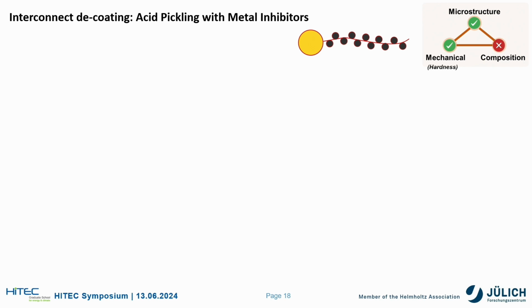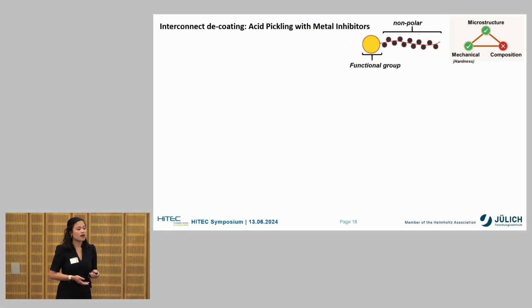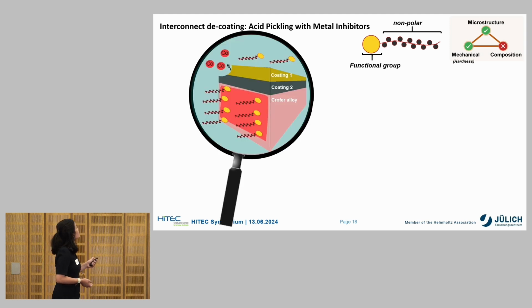The mechanism of these inhibitors are quite complex to discuss, but to put it simply, these are organic compounds that have a functional group that adsorb or react on the surface of the Crofer alloy, forming a thin protective film that protects it against the acid. Meanwhile, this oxide coating, due to its different electrochemical property, continues to get exposed and dissolved by the acid.